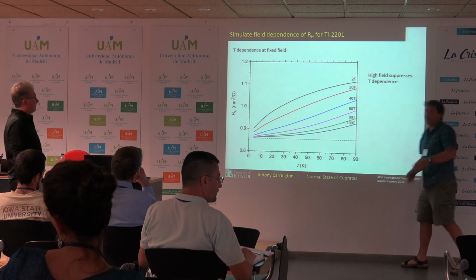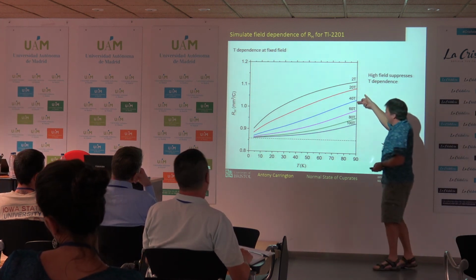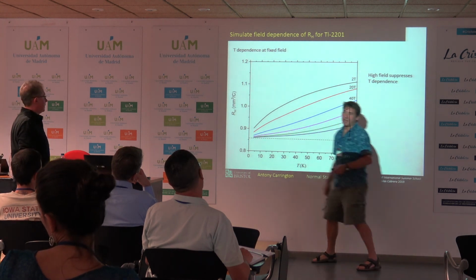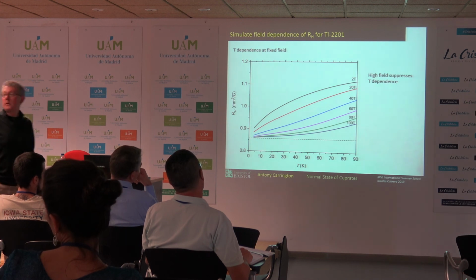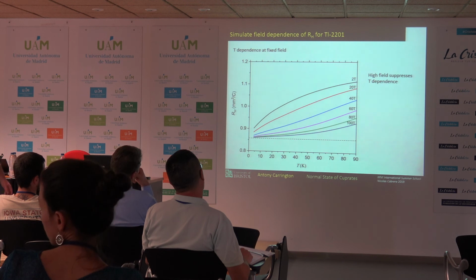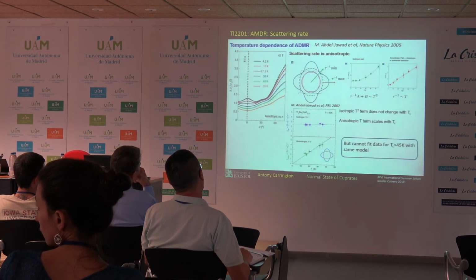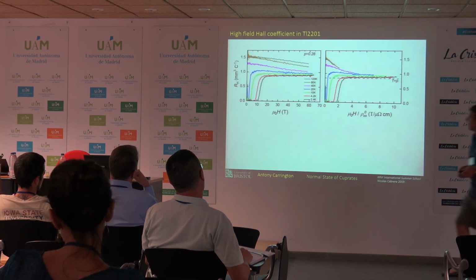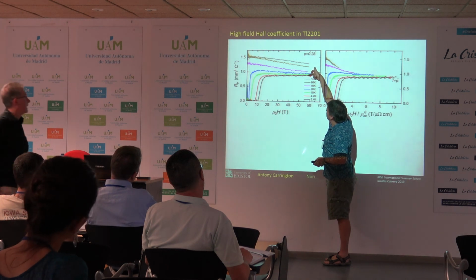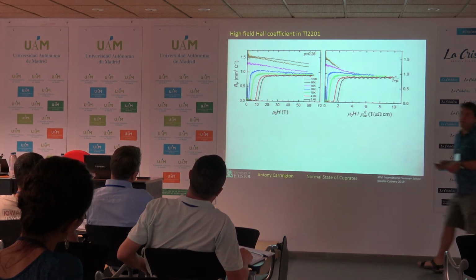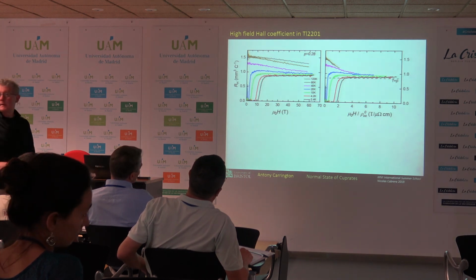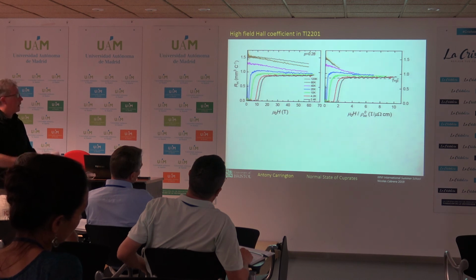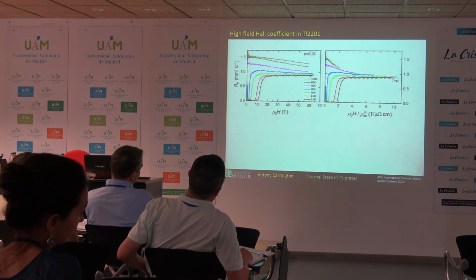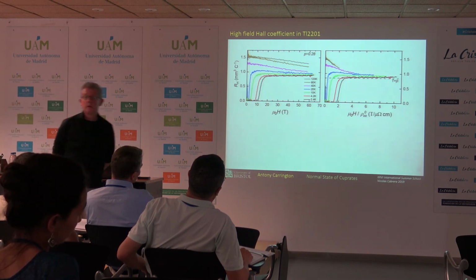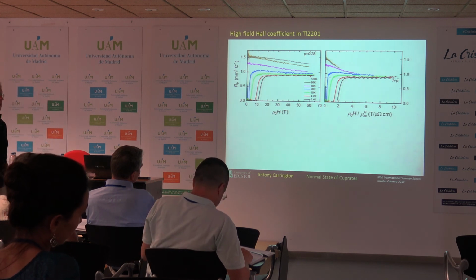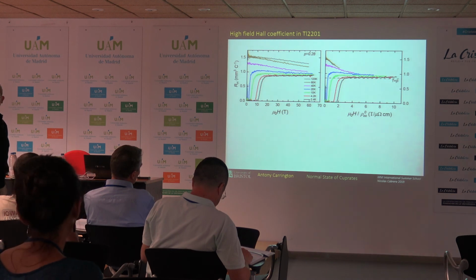So you've got this field dependence, but of course you can't extrapolate to infinite field. So what you have to do is use high field but also low temperature. And the combination of the two is what you use to try and find what the limit is. But in magnetic field, the slope changes significantly. So that's what I tried to show. You've got this slope, but as you go to low enough temperature, it becomes flat. So at low temperature, you've essentially got isotropic scattering again. You've got two things which are helping you. The scattering is becoming more isotropic because the temperature-dependent parts have gone. And the second thing is you've got high omega_c tau, which is averaging it all out anyway. So you need both things to effectively get the T to zero limit.